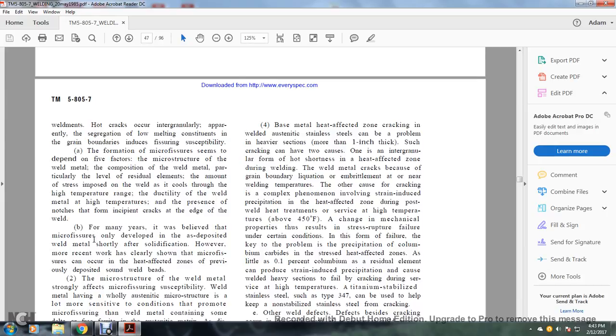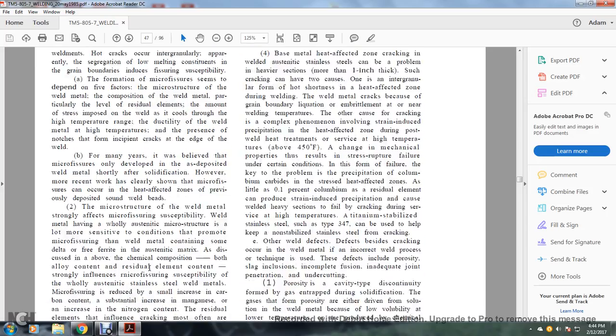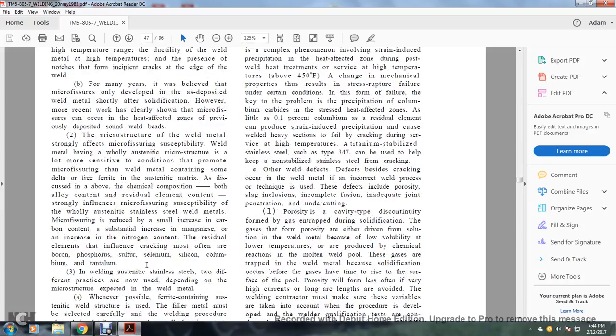Microfissures develop in the deposited weld metal shortly after solidification. However, the most recent work has clearly shown that microfissures can occur in the heat affected zones of previously deposited sound weld beads. The microstructure of the weld metal strongly affects microfissure susceptibility. Weld metal having a wholly austenitic microstructure is in the most sensitive condition and promotes microfissuring, while weld metal containing some delta or free ferrite in the austenitic matrix resists it.